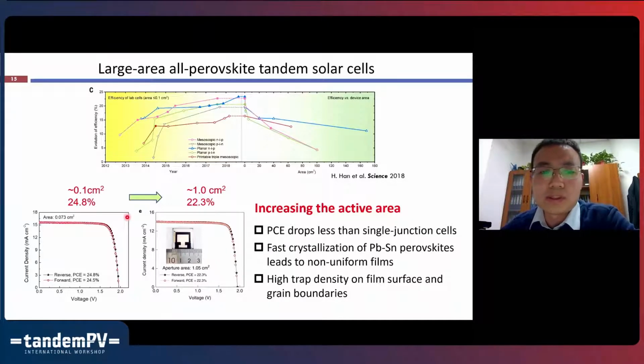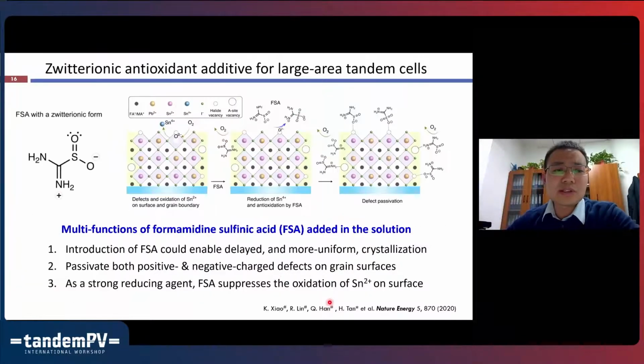So this is mainly due to the non-uniformity of the narrow bandgap perovskite because of its fast crystallization and also the high trap density on the film surface, and also, we think, in the grain boundaries. So one strategy we think is that maybe we can find a passivation agent that can also modulate the crystallization process itself. At that time, we found a molecule called formamidine sulfinic acid,